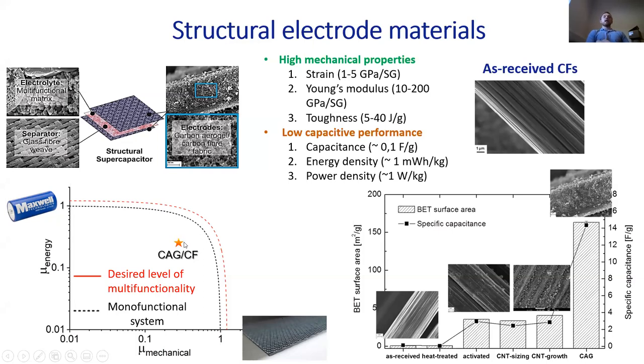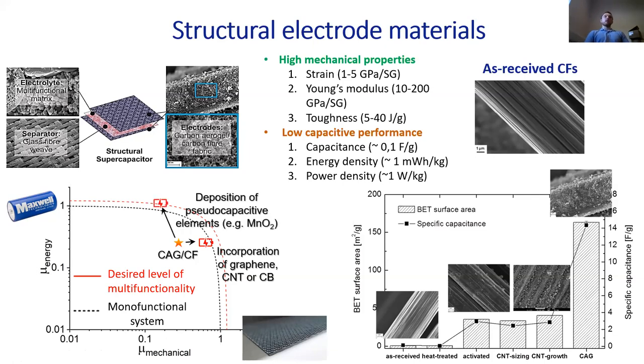So the question is how we can further improve the performance of this system to cross this line and basically achieve the weight savings. The first possible method is incorporation of nanocarbons inside of the carbon aerogel and carbon fiber pores, which can slightly increase the electrical conductivity, but more importantly, can lead to some improvement of mechanical performance. Another route, which was partly presented by Servann, is the deposition of pseudocapacitive elements on the surface of carbon aerogel pores and carbon fibers.